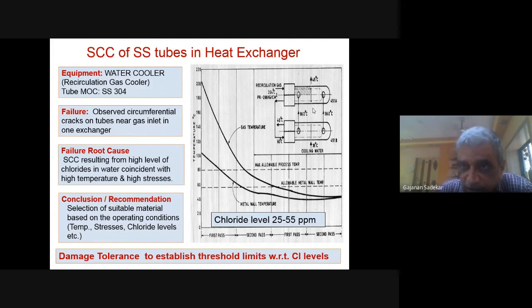Then I removed the scales which were formed on the tubes, and then I could find the cracks on the tubes. So immediately at that time I want to tell you something. I was very young at that time, but I said it's stress corrosion cracking, because I knew a little bit about stress corrosion cracking. This problem got solved in the sense that, as far as the customer was concerned, they had supplied tubes to us. They had supplied the design to us. So I came out. But afterwards, I started studying why this failure has occurred only in that much zone.